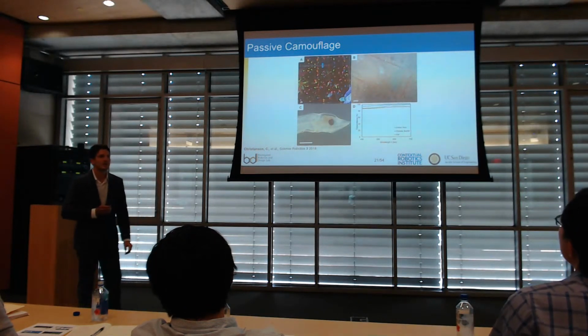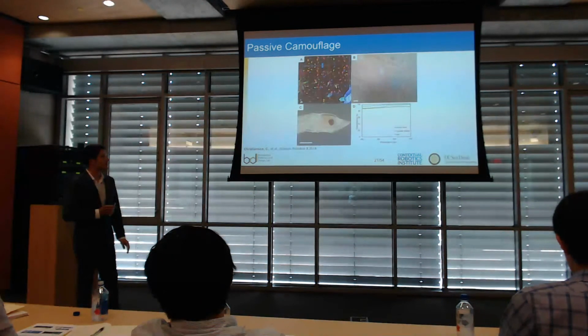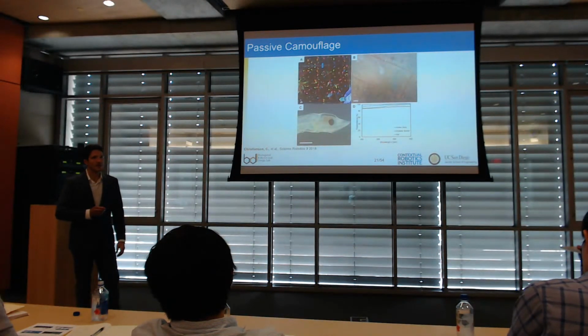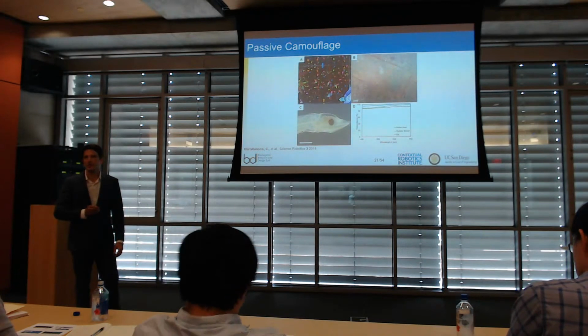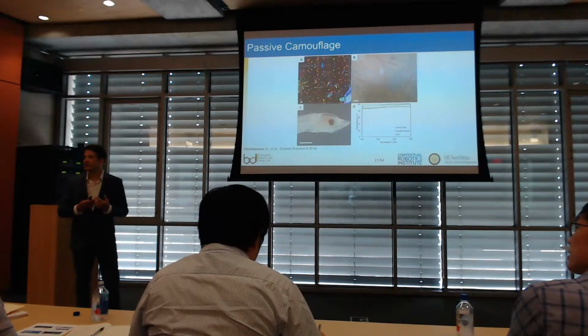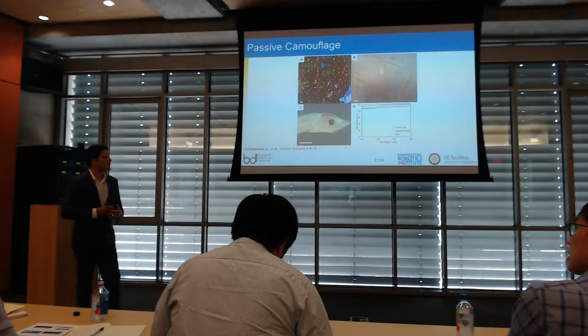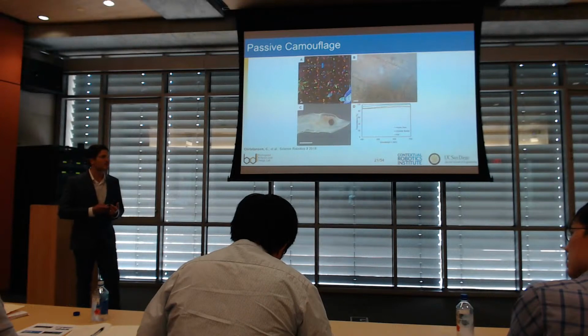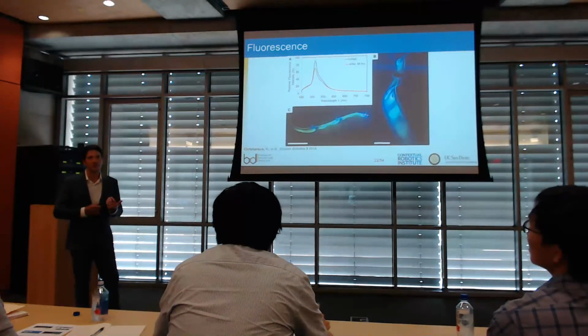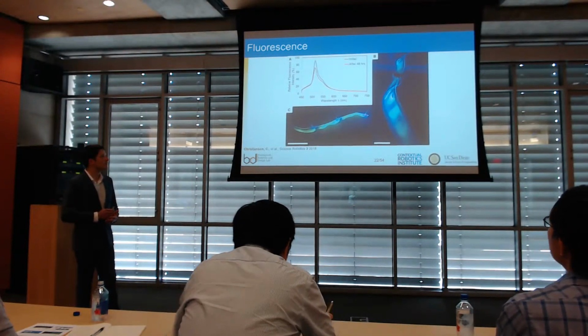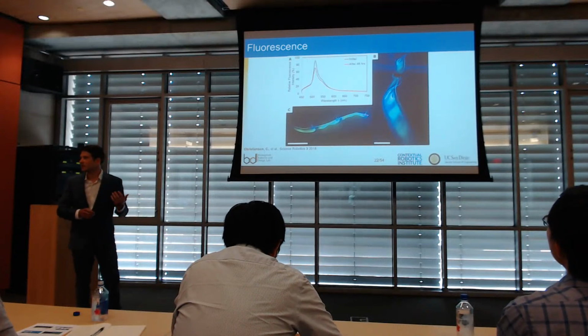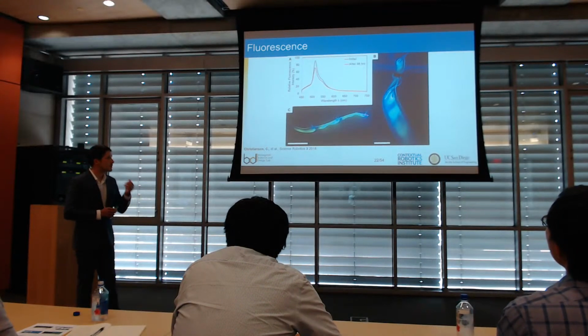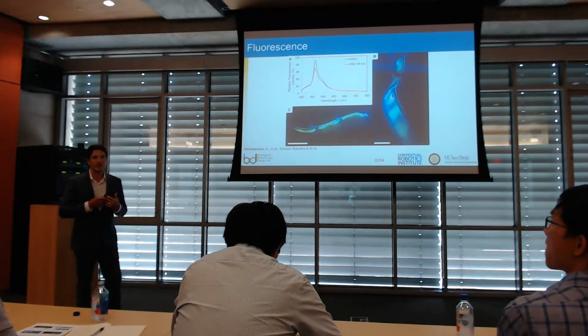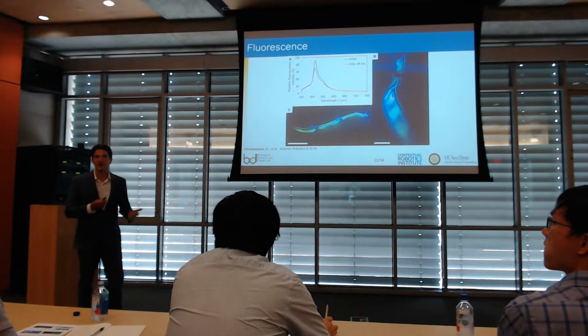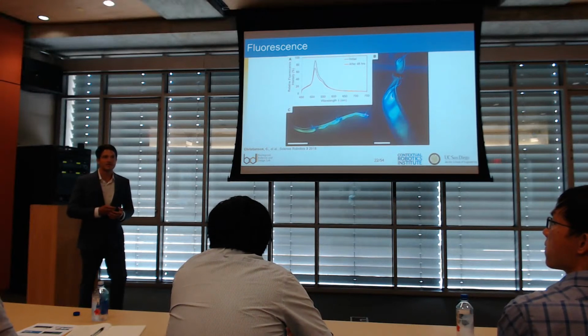So if it's transparent, we want to see if we can do something interesting with it. And we found that there's eels in nature that will biofluoresce. So under moonlight, they will actually glow, or fluoresce, or luminesce, I'm sorry, bioluminesce. And so we wanted to see if we could capture that with our robot as well. And so we loaded our robot with a fluorescent dye and then stimulated it under black light and showed that we could get it to glow. One of the reasons that they believe that the eels have this ability to fluoresce is so that they can find each other at night during spawning events.